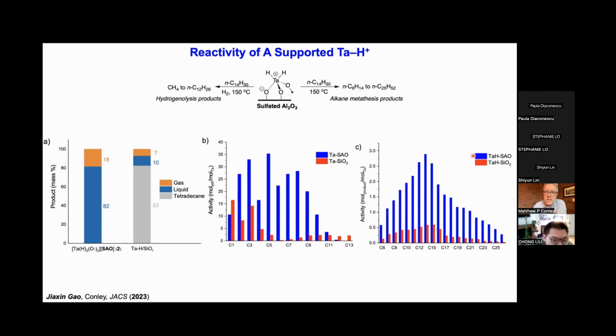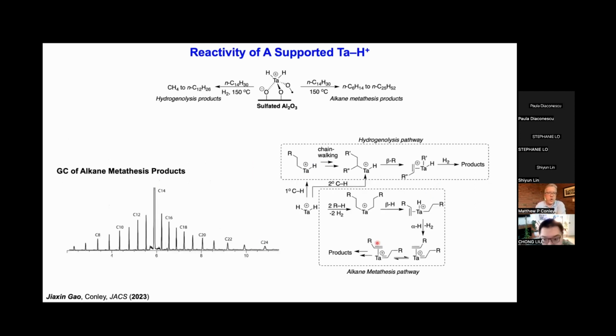So again, we see the tantalum hydride on sulfated alumina is significantly more active in this reaction than the tantalum hydride supported on silica, which is in line with the hypothesis that installing charge on the metal should affect these various rates. So how do these reactions work?